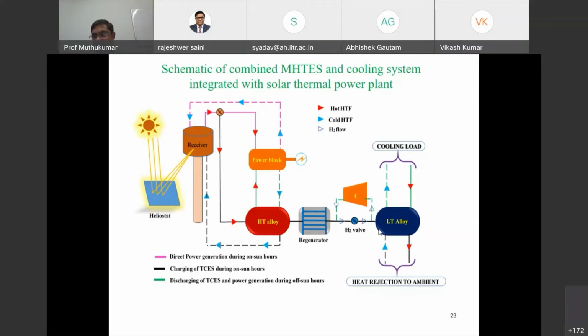Okay, so this cooling effect will be almost equivalent to the amount of heat which you have supplied to the high temperature alloy. Almost the same, maybe it may not be the same, but slightly less. But you will be getting a huge amount of cooling effect at about 10 to 15 degrees. Then since we have a compressor here, you boost up the hydrogen pressure from 1 atmospheric pressure to about, say, 25 bar. Okay, I'm giving an example. Then you pass it through the regenerator, because when you are desorbing, the hydrogen will be desorbed at 350 degrees Celsius. The heat carried away by the hydrogen gas will be stored in the regenerator. It may be a small quantity, but still you can make use of it.